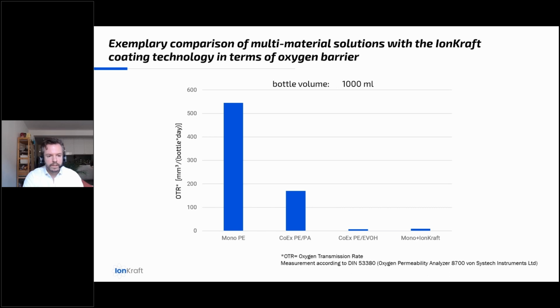Here you see an exemplary comparison of common multi-material solutions with our coating technology in terms of oxygen barrier. What we can see is, OTR stands for oxygen transmission rate, and the OTR of the monomaterial polyethylene is shown. So it's a polyethylene bottle, in this case mostly used for agrochemical purposes. And you can see here the comparison to the co-extruded polyethylene polyamide multi-material, which brings an improvement of barrier of roughly threefold.